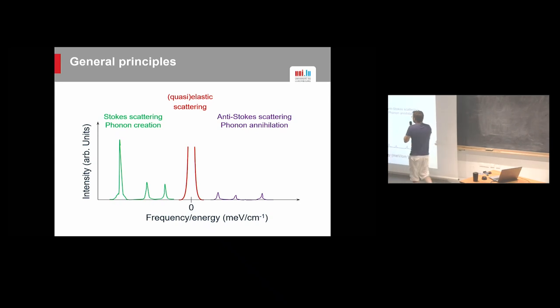But in principle, if you're only interested in the frequency, the energy, it's enough to measure only one side. Okay? So in Raman spectroscopy, we typically only measure that, unless we have a very good reason to do otherwise. In Brillouin spectroscopy, they systematically measure both. Neutron as well, we would measure that. So then practical considerations come into play for that choice.